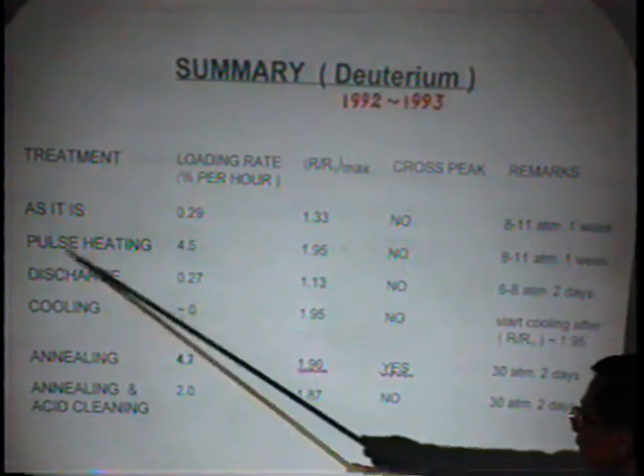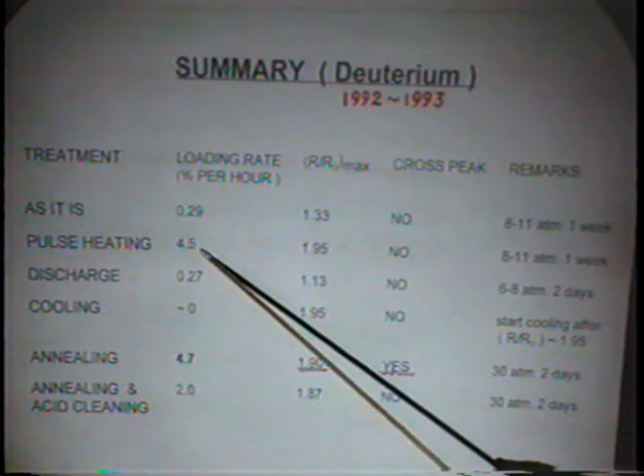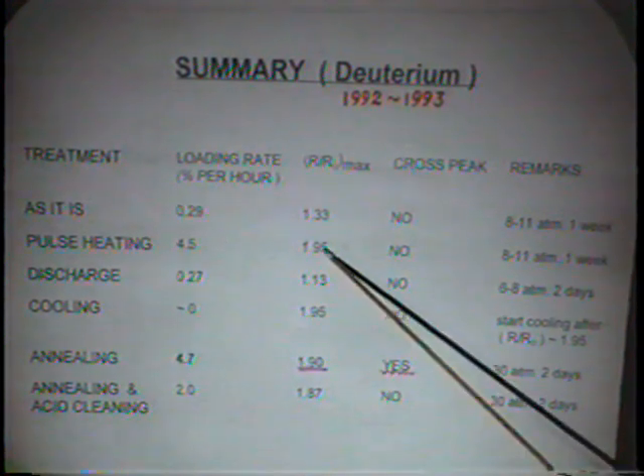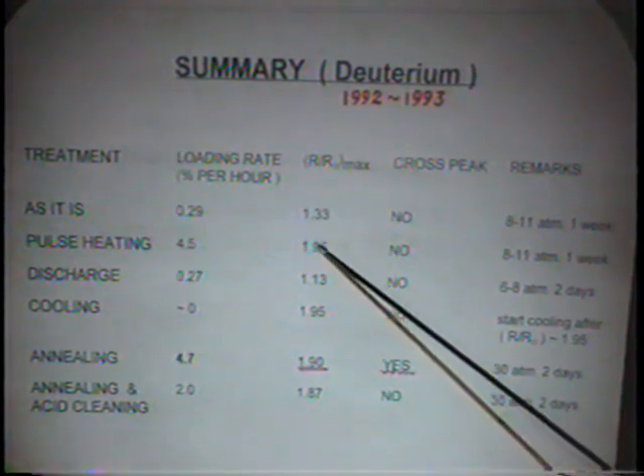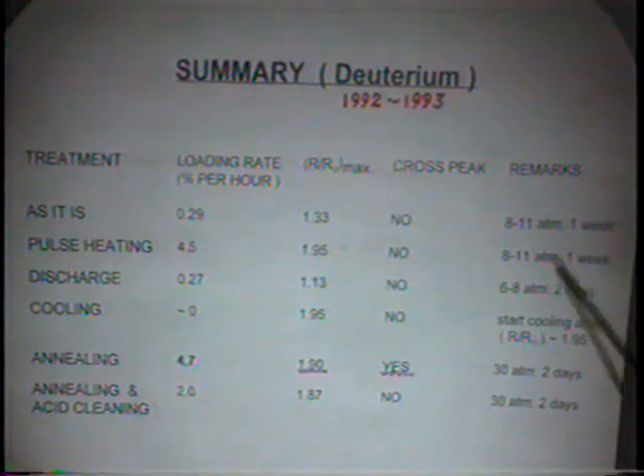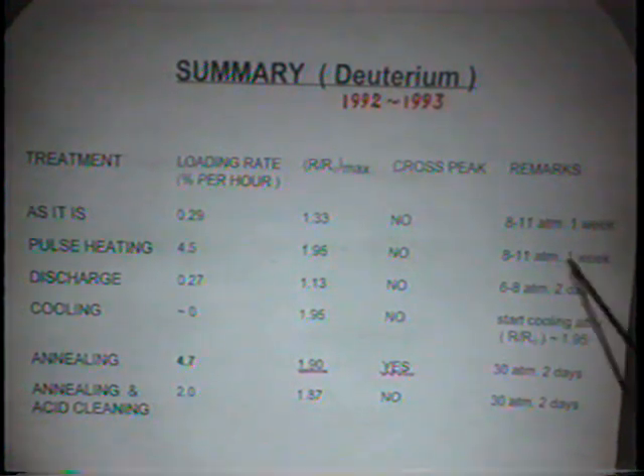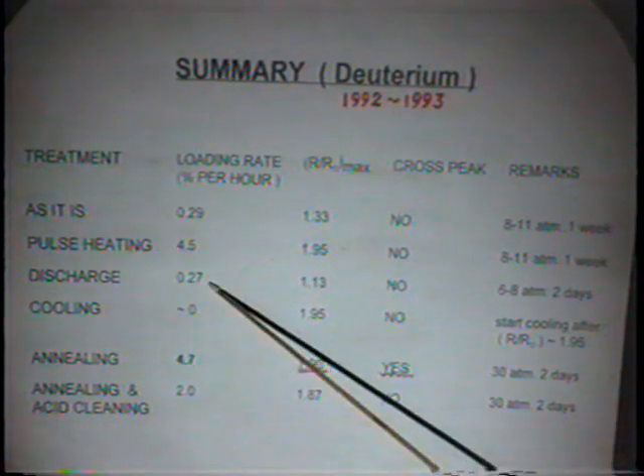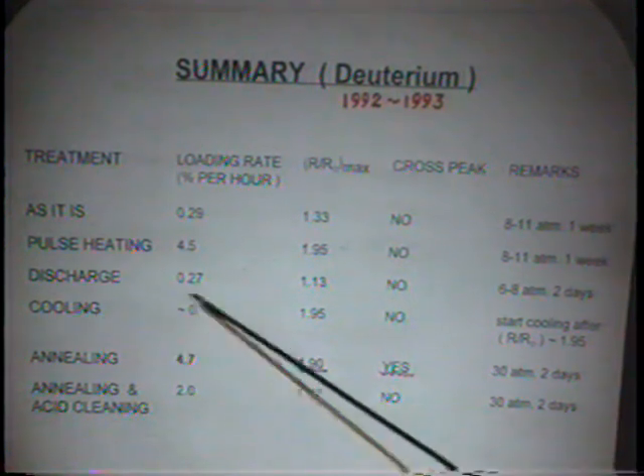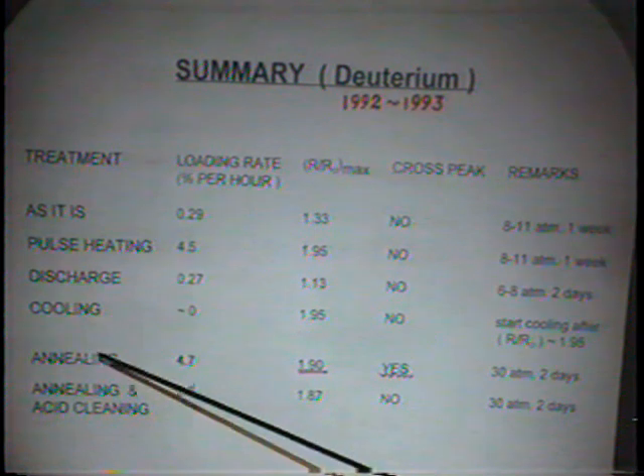The pulse heating can increase the loading rate very quickly, but the maximum is 1.95, it's still not on the other side of the peak because the pressure is too low. Then we use discharge. Discharge effect is small. Cooling effect is small. The annealing is most important.